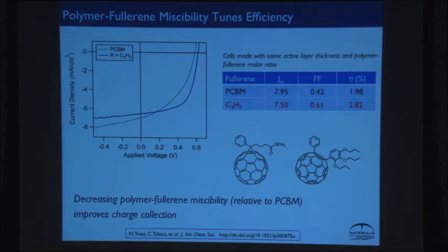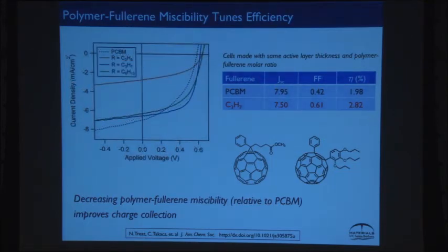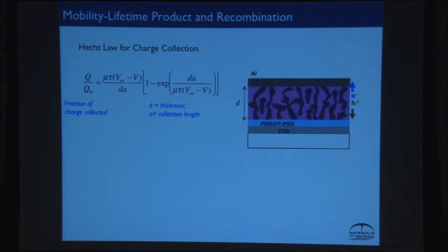A little bit of VOC improvement, but not much. And then when we look at the other fullerenes, we always saw reduced fill factors with the other side chain lengths. Okay? And what we found was that it correlated pretty well with our hypothesis that you had to have a certain amount of miscible fullerene and a certain amount of the precipitated fullerene. And so when we looked at this, we said, well, how are we going to model this?